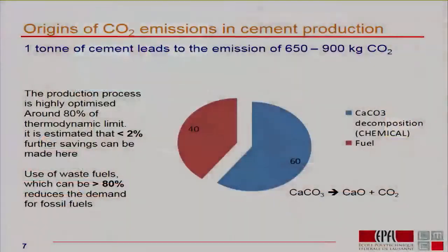chemical CO2. That's to say that the first stage in the production of cement is we take limestone, which is calcium carbonate, and the calcium carbonate decomposes to give us calcium oxide and CO2. And that accounts for 60% of the emissions. Now, if we're going to change that, the inevitable consequence is we're going to change the chemistry. And if we change the chemistry, then the whole way it reacts and performs is going to change, and that's why we need research to find out what differences these things make.